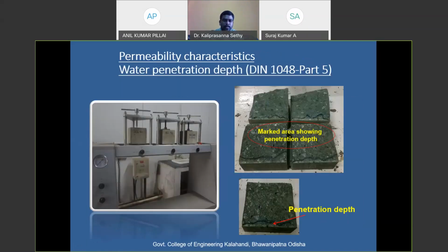And this is another permeability apparatus to ensure more about the permeability. We have conducted another test for permeability characteristics as per DIN 1048 part 5. You can see at a time we can check 3 samples. With a 5-bar pressure, we fixed the samples in this apparatus and kept them for 72 hours, and the pressure drop is checked throughout the process. After 72 hours we took the samples from the apparatus, and we broke the samples.